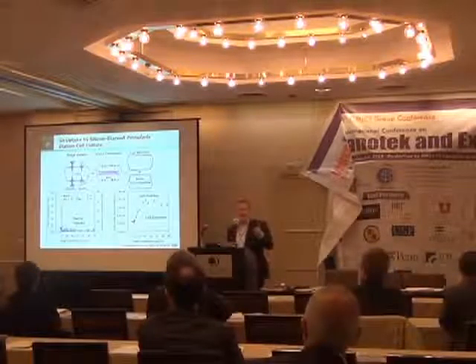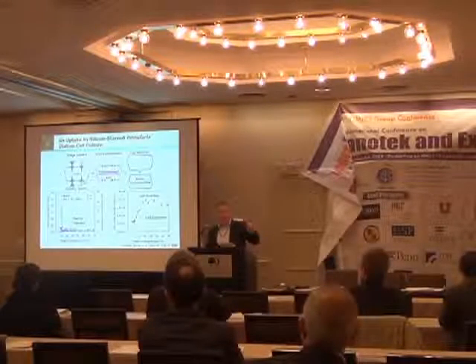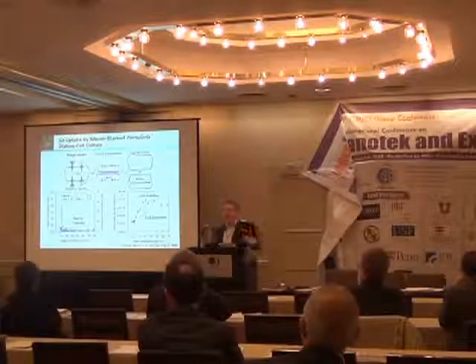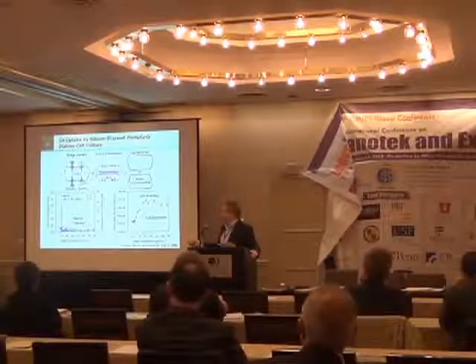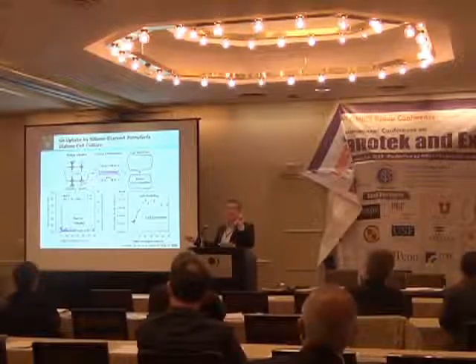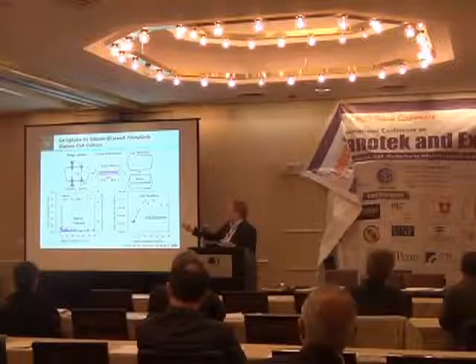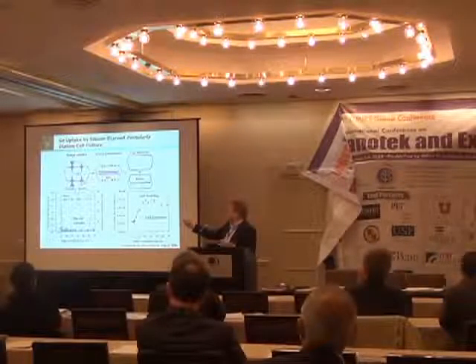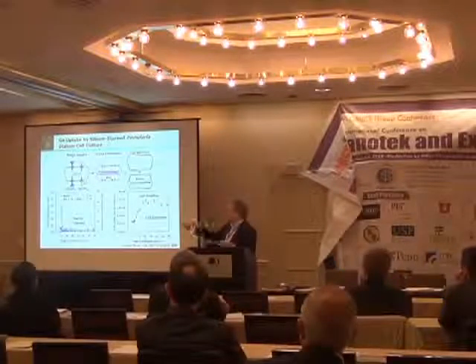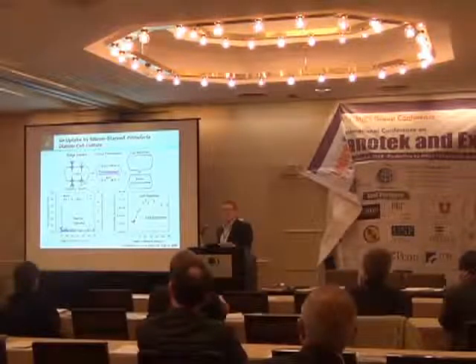We can control this process by determining when in the cell cycle the organism is most likely to take up a foreign metal, and then controlling the ratio of those two metals and the total amount added, to design a certain composition and production capacity for making these nanophases. In this particular experiment, we added enough silicon so that the cells would undergo just one cell division. The organism takes up silicon to make a second shell. If we add germanium concurrently, we can make a silica-germanium nanocomposite on one side of the organism with a designed composition.